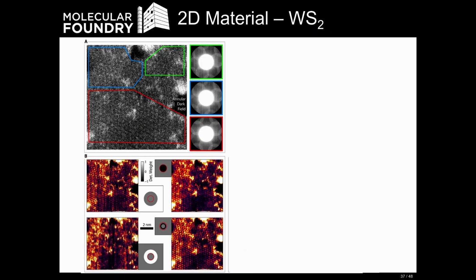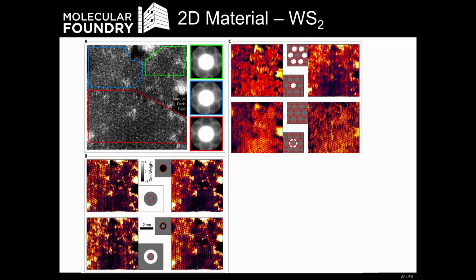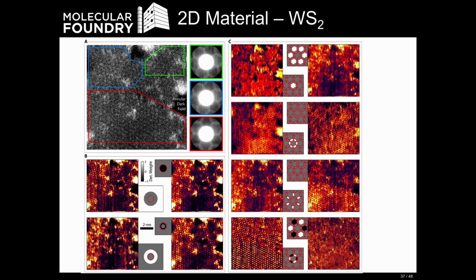And so we're not limited to circular apertures, of course. I can make arbitrarily complicated images in diffraction space here, showing, for example, the unoverlapped disk regions in dark field or bright field, or below in this panel, the triple overlap or double overlap regions. And you can really see that atomic resolution contrast in coherent diffraction imaging does come from the overlapping scattered Bragg disks here. It's these double and triple overlap regions that lead to our atomic resolution contrast. And of course, you can do arbitrarily complex ones where you subtract some regions and add other regions, and you can form almost any type of virtual image that you would like. And so this, again, is all one data set, a single experiment recorded in three minutes on our K2 camera on the aberration-corrected TEAM 1 microscope.